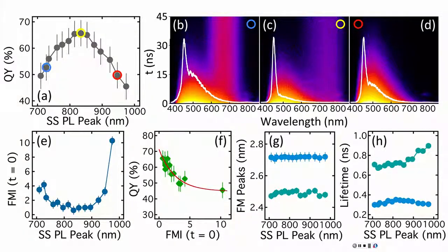The question is, what is this fast decay? It's either surface states or some kind of direct transition. But there was also a lot of discussion about oxygen impurities. There's no oxygen in this problem. The way we've done this, we've done all the synthesis, size separation and characterization without ever letting them see air. It's been quite a challenge. But there still might be surface states because you cannot completely control the surface.